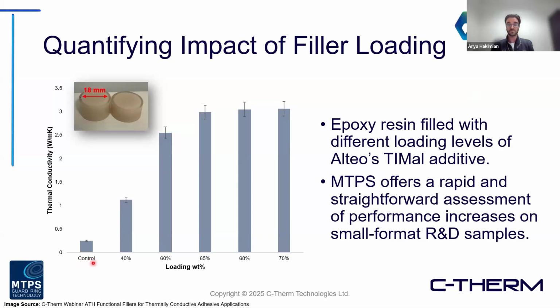So again, a very straightforward data set here, but just looking at the control. This was an epoxy-based resin that we tested, and then added various loading levels of the Alteo filler. And, as you would typically expect, there's a net increase in thermal conductivity, increased heat dissipation up to a certain point, and then we maybe see some diminishing returns at the upper end.